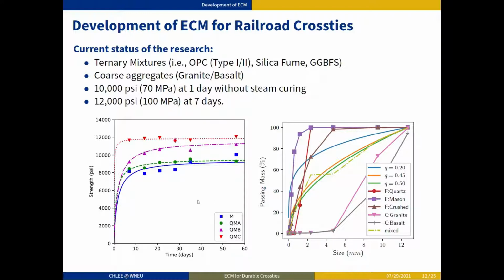In addition to carefully selecting all the mixture ingredients, we try to achieve the optimum size grading curves. I will briefly explain later how we are going to consider surface area of the aggregates, but at least by using the conventional method, using the aggregate size distribution, we try to achieve the optimum packing density. The Q value shown on the right panel of the slide indicates the distribution parameter. As the Q value gets smaller, the grading distribution goes up and up on the right panel.